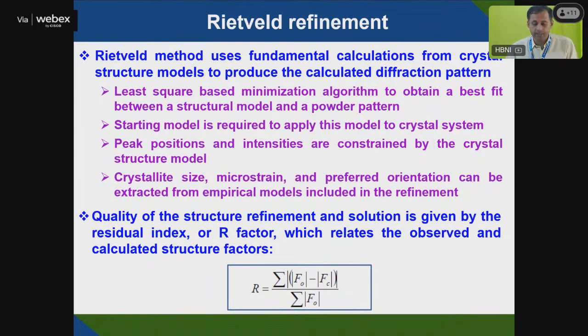So I will not discuss Rietveld analysis in detail because of time constraints. By using a proper Rietveld method, there is a fundamental calculation from the crystal structure, and you can produce a model to produce a calculated diffraction pattern. Using theoretical data, with peak positions and whether it's FCC or BCC based on your knowledge, you can draw, with fundamental calculation from the crystal structure model, a calculated diffraction pattern. Then you can compare your calculated diffraction pattern and your obtained diffraction pattern.